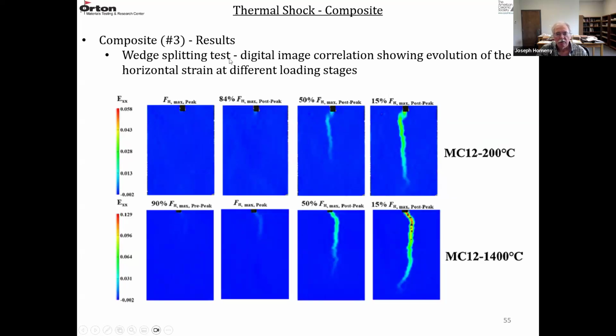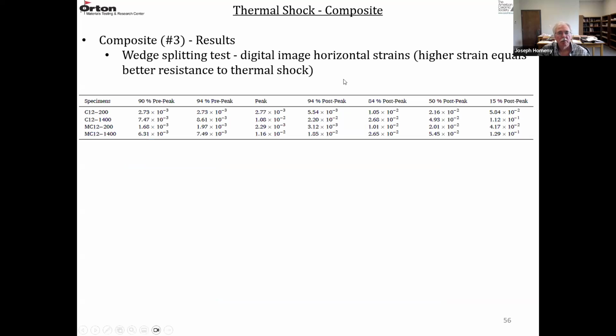And then this is the evolution of the crack in the MC12 material at 200 and 1400 degrees C. And again, here's the peak levels, and then here's where the crack starts to grow after the peak. And down to 15% load, you can see the crack patterns. So these digital images give you the horizontal strains. The higher the strain, the better the thermal shock resistance. The more strain the material can take under stress, the lower the amount of damage that takes place.